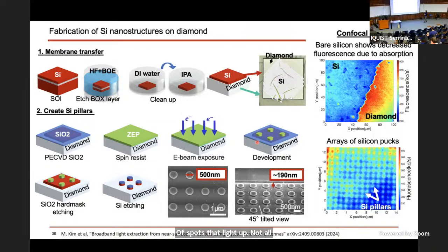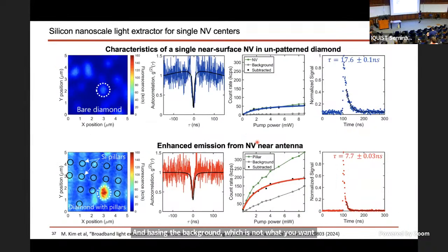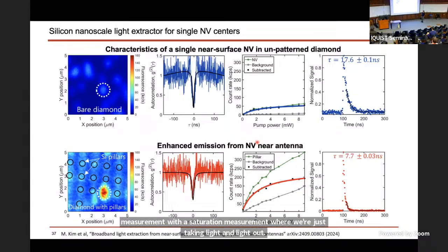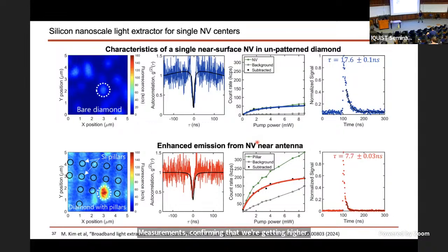Not all are NV center emissions. Some, we're just actually enhancing the background, which is not what you want. But for a couple of pillars, we actually found nice enhanced single photon emission. We confirmed that with second order autocorrelation measurements, and with a saturation measurement where we're just taking light in, light out measurements, confirming that we're getting higher counts. And then we also saw some shortening of lifetime.